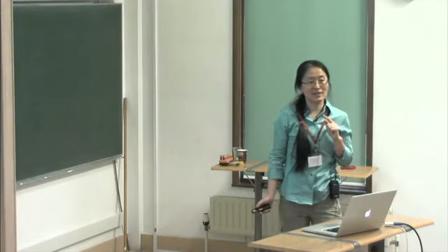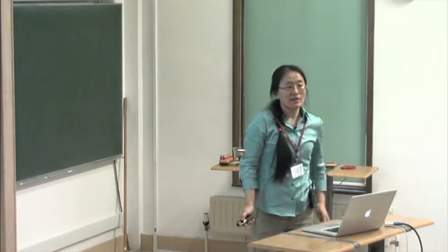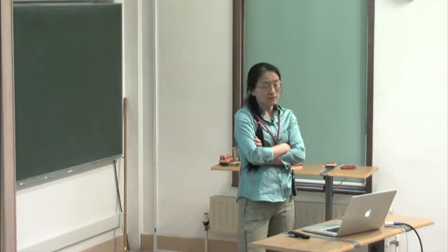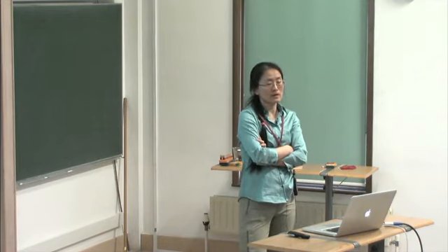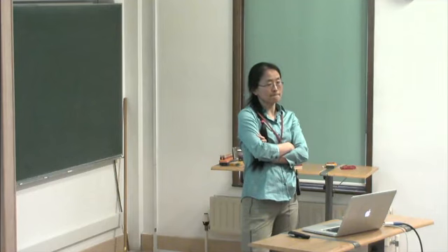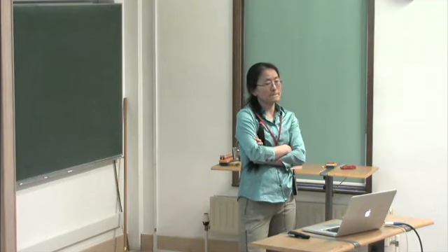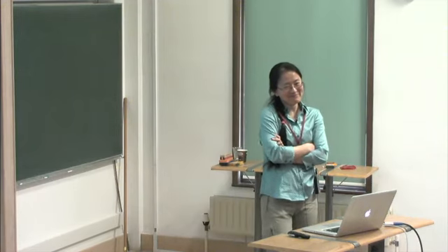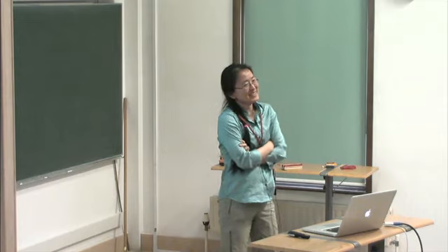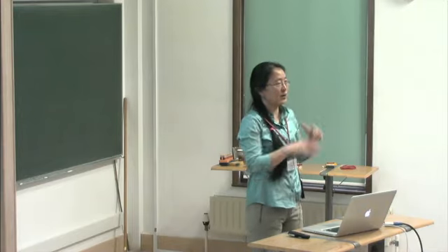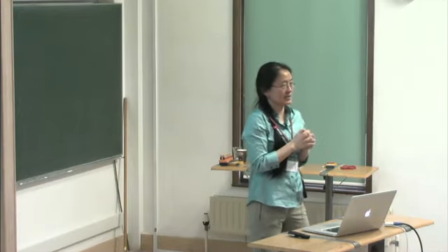They can't scale the same way, because the conductivity must go essentially as the cross section through the melt, and it doesn't matter how it's distributed. Whereas it matters very much how it's distributed from the point of view of the permeability. So the answer is no. It seems to me the answer is no. I'm just saying that you see how the Ohm's law we use to get the conductivity.